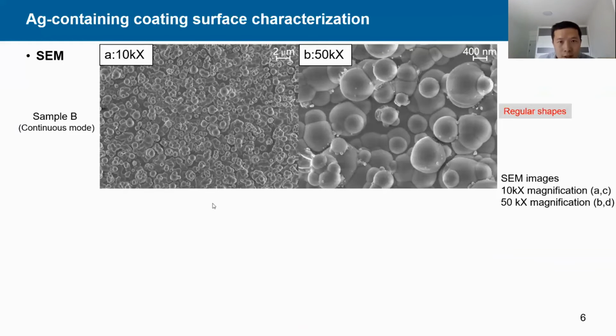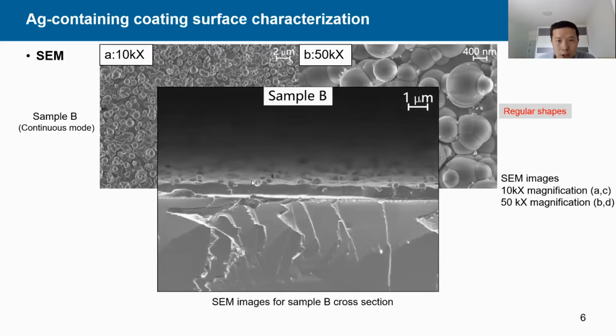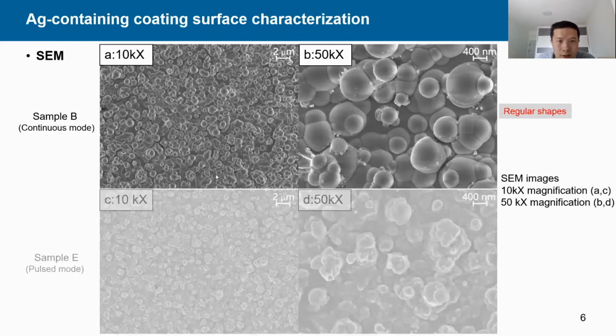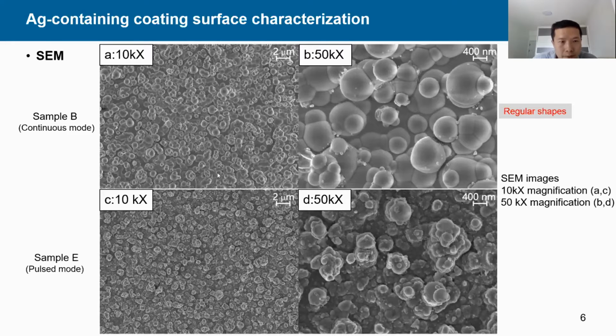simply we can see here the same image of sample B in the continuous mode, we see quite big nanocapsules or nanospheres in the coating with regular shapes, and we also checked the cross section of coating and found that the nanospheres were embedded in the coating or also grafted on the surface. And when we check the samples in the pulsed mode, like sample E, we can see smaller nanospheres on the coating.